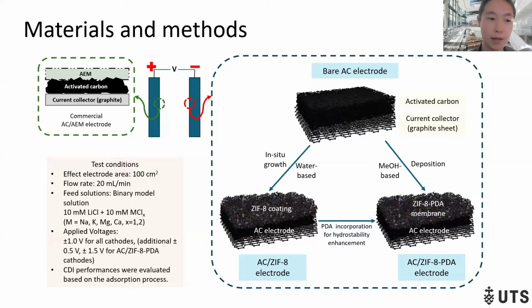And the test condition was a flow rate of 20 milliliters per minute, and the model solution for the feed is a binary solution containing lithium and another competing ion.